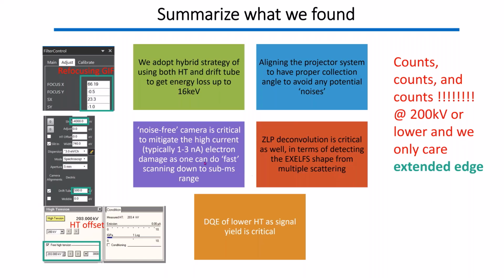Also, noise-free cameras are very critical to mitigate the recurrent electron beam damage, not only for signal to noise, but also because you can do fast scanning. We typically do sub-millisecond scanning, so that it can accumulate enough signal without bothering about noise. And again, we're talking about how many counts, how good a signal to noise we can really get. So in that sense, we will have to go to a bit lower high tension, let's say 200, or at least that's what we chose to do. And the DQE of the camera at the lower high tension, depending on how good a sample we can have, is very critical.